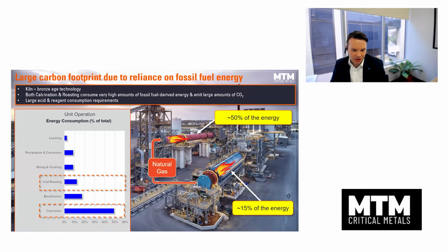And not just the calcination step requires lots of energy, also the acid roasting, where you basically roast the lithium in a sulfuric acid environment to turn it into lithium sulfate. And then the subsequent steps involve pulling out the impurities from that lithium sulfate. So it's a very energy intensive and reagent intensive process. And the kiln is the dominant heat transfer medium used here, and that kiln technology has been around since the Bronze Age. So it's not exactly new technology.